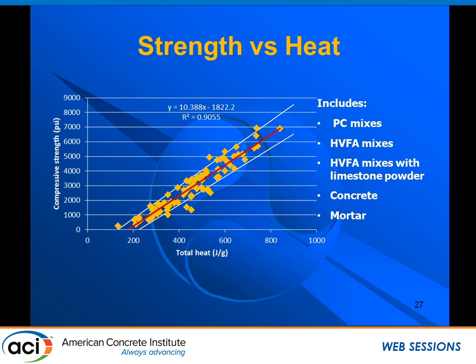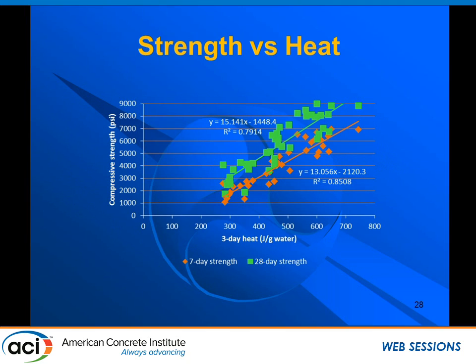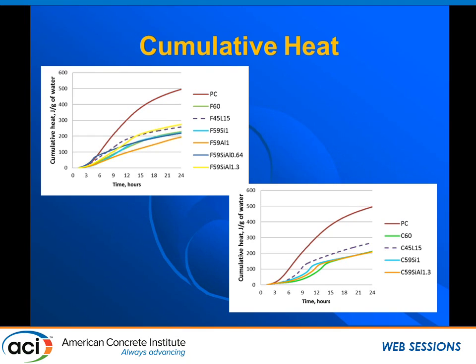I had only up to 72 hours, so I decided to plot differently. I used the 72-hour total heat to come up with two other curves to predict compressive strength either at 7 days or 28 days.